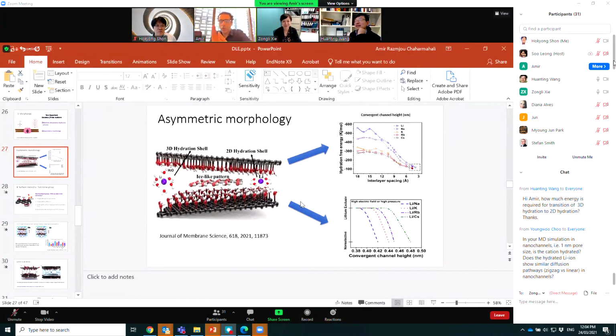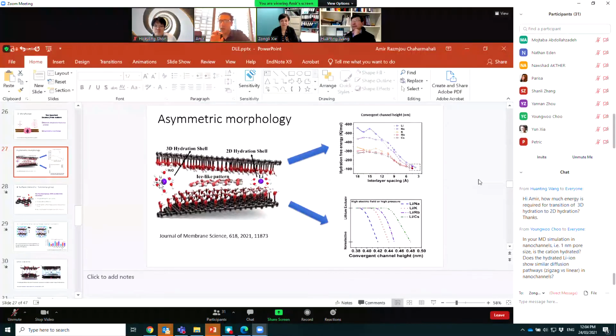That's a very good question, Professor Wang. What we found is that when we create this sort of asymmetry, even with a low current and low potential across the membrane, it helps you overcome the hydration energy, the change in the hydration shell. We also calculated that in our publication, and I can send you more details later on. If you design it this way, you don't need to apply too much energy to overcome this hydration energy.